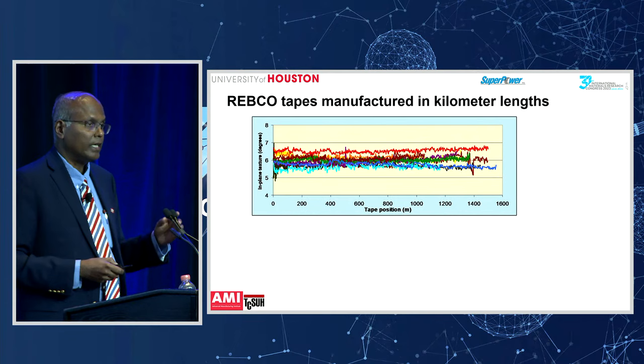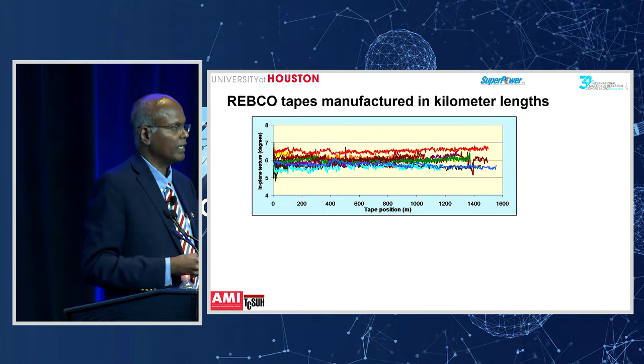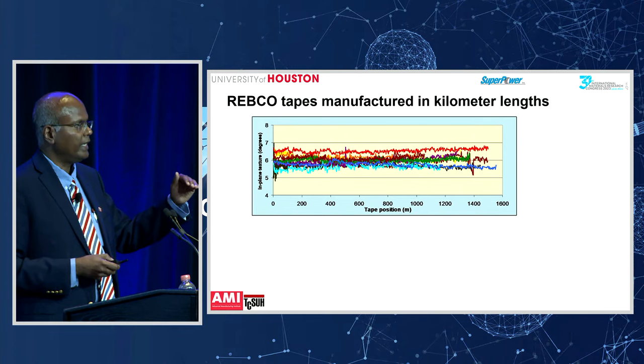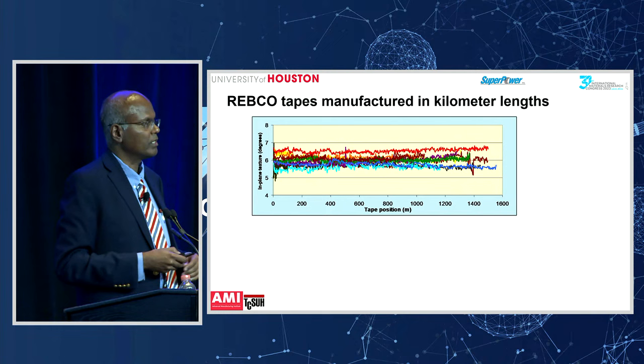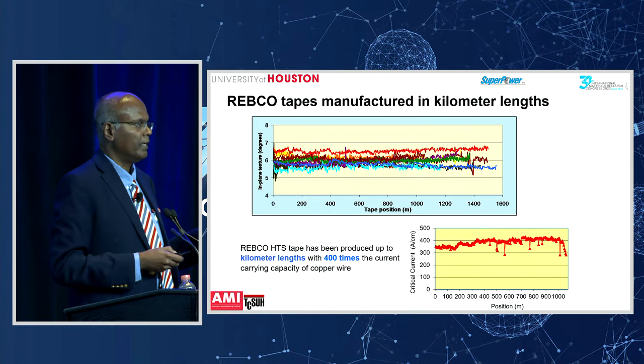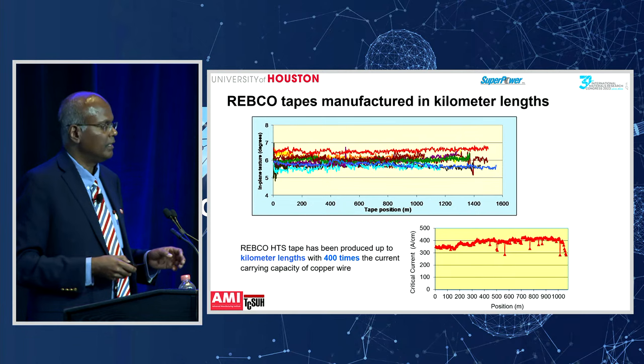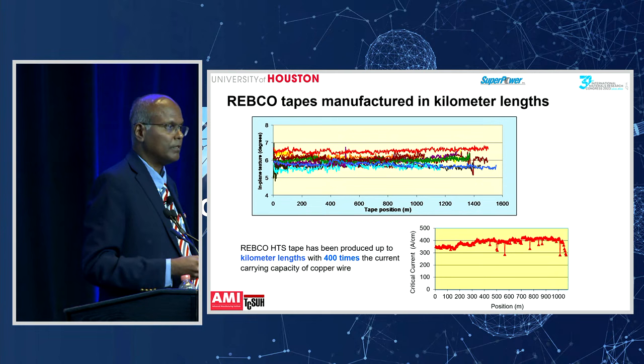It was successfully done. As Professor Hare mentioned, I was previously at the company SuperPower, and we were the first ones to actually make this in a length of a kilometer. That is the buffer tape, the buffer film, over a kilometer, 1.4 kilometers. And you can see the grain-to-grain misorientation measured by X-ray diffraction continuously over a kilometer. It's about 6 degrees, which is pretty good. And then when you grow this epitaxial film, in this case by metal organic chemical vapor deposition, or MOCVD, you can see a kilometer-long tape with good current carrying capacity. So this technology was developed, again, 15 years ago.